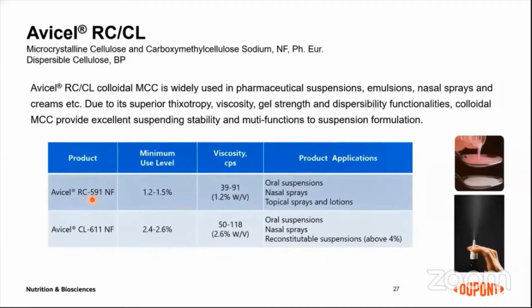There is more CMC content in this product grade, which could be used for oral liquid suspension as well, but we can also recommend it for reconstitutable suspension, though the use level is a little bit higher than a typical liquid suspension. It's about 4%. But with CL611, the formulators don't need to do high shear dispersion, which is different from the first product grade, RC591.